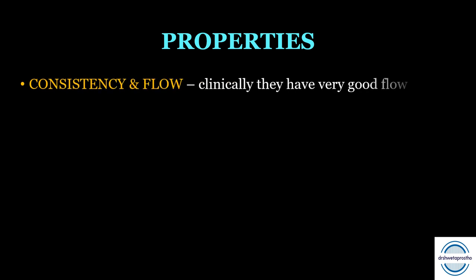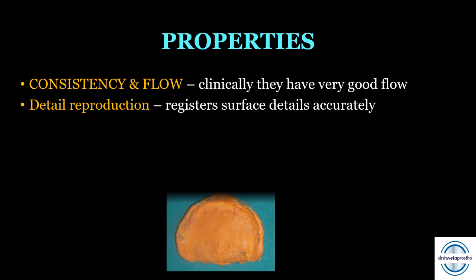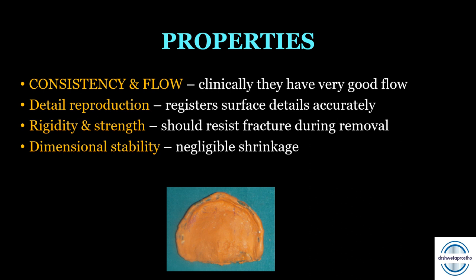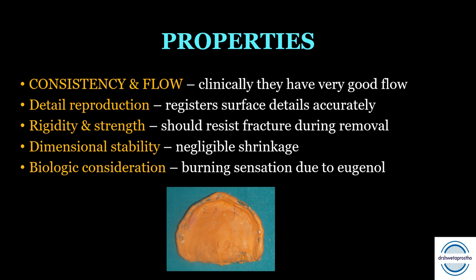Properties of ZOE impression paste: Consistency and flow — clinically it has very good flow. Detailed reproduction — because of good flow it registers surface details accurately. Rigidity and strength — it should resist fracture during removal; compressive strength is around 7 MPa two hours after mixing. Dimensional stability — quite satisfactory, with negligible shrinkage of less than 0.1%. Biological consideration — the paste causes burning sensation due to eugenol, which can cause tissue irritation; non-eugenol pastes can be substituted.